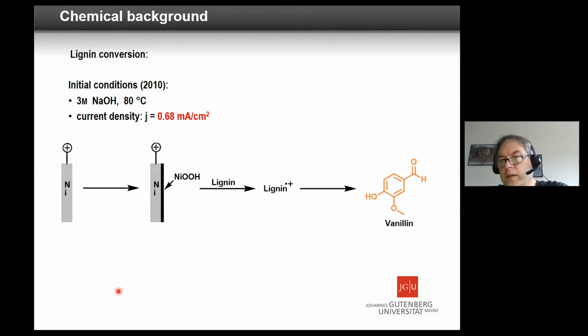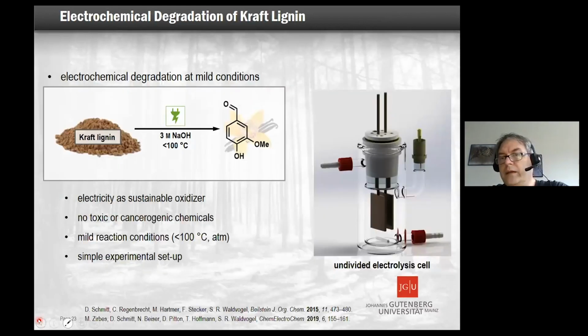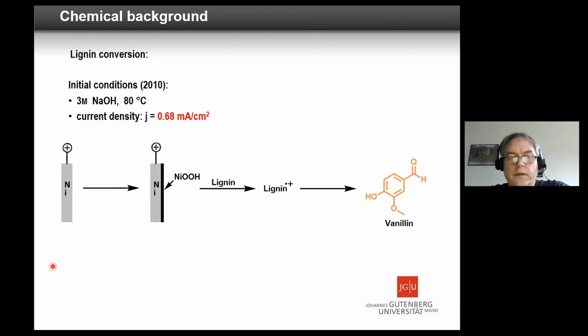It turned out the best way to do this is that you have an active electrode. And the active electrode is, for example, nickel or other metals. On the surface, under alkaline conditions, you have a nickel oxide hydroxide, and this is a strong oxidizer. And this lignin is then converted, makes a lignin plus, something like this, and this disintegrates and forms vanillin. And you see, this was found some years ago, and here you see this is already in a way that we can say, okay, this is easy to handle.